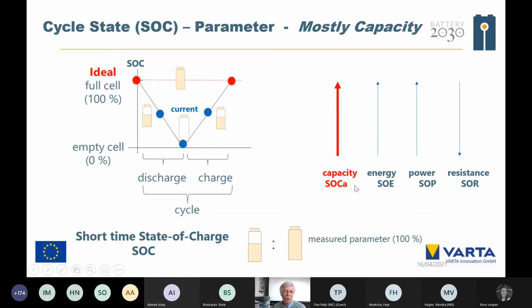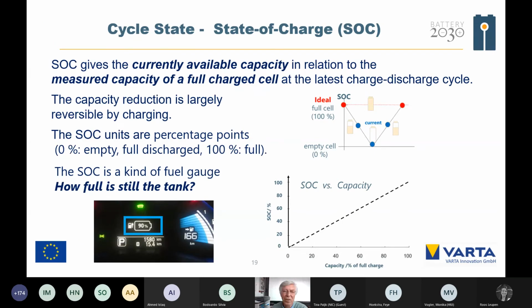In nearly all cases, for the characterization of that states, let's say 50% state of charge, we use the capacity. And therefore, if we are speaking about the state of charge, that means in nearly all cases the state of capacity. That means the state of charge means practically a state of capacity. So the state of capacity gives you the information about the currently available capacity in relation to the measured capacity of a full charged cell. The capacity reduction, up to that one, is largely reversible. So you have no big changes between that capacity and that capacity, practically no changes in one cycle.